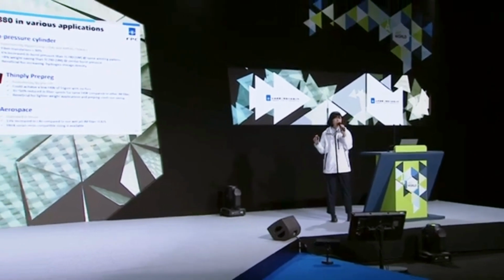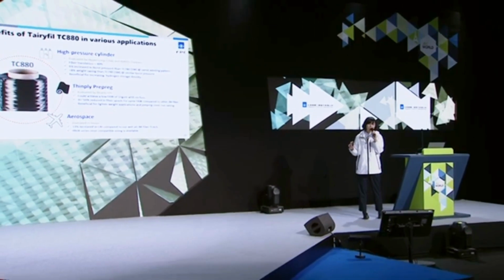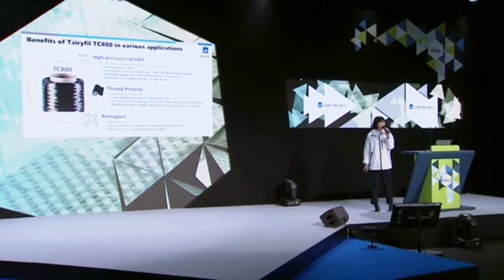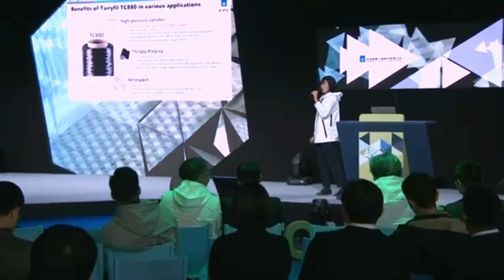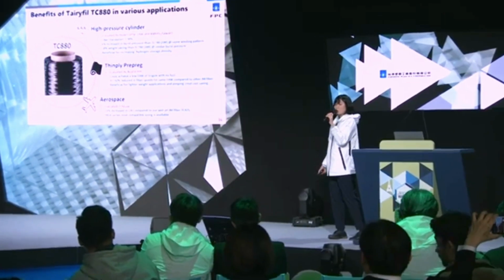And for thin ply prepreg, it has already been evaluated by a bicycle OEM in Taiwan, and it could achieve a low fiber areal weight of 55 with no fuzz occurring. And to achieve the same FAW, we could save 30% to 50% of spools because we have a higher yield. It's also beneficial for lighter weight and also saves creel cost. And for aerospace, we already evaluated in-house, and we can see a 13% increase in compression after impact, CAI, which is crucial for the aerospace industry. Also for thermoplastics, we already prepared the compatible sizing for this field.